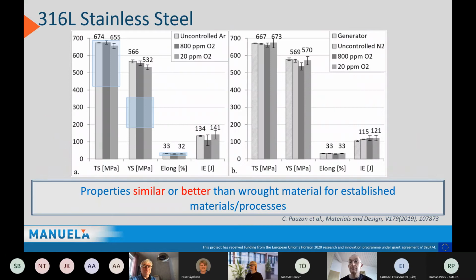Next slide, please. And that can be shown here. If we just take some examples, taking 316 stainless steel, austenitic stainless steel, the typical sort of stainless steel for a lot of applications. Here you see a number of data: tensile strength, yield strength, elongation to fracture, and impact energy. And you can see that there is quite a small spread.